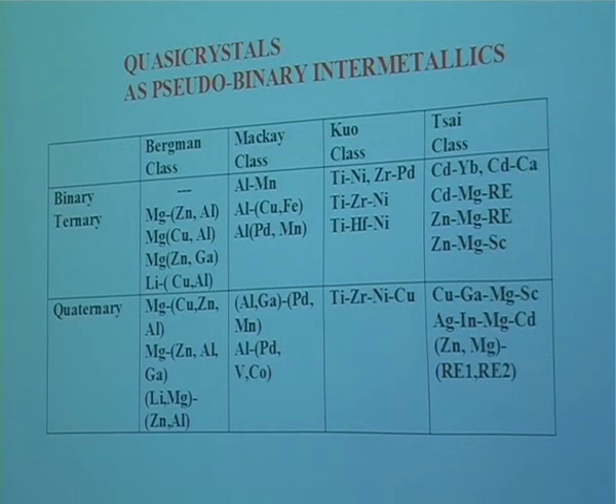So I think it's a very important contribution from our side that we can understand all the quasicrystal structures as being either binary or pseudo-binary intermetallics. We have gone on further to show that if you want to produce a glass, you have to go for a ternary or a pseudo-ternary alloy. That is, a crystal structure is able to sustain two different types of atoms. But if you put a third one, which cannot fit into this category, then the crystal or quasicrystal structure is destabilized and you result in a glass.